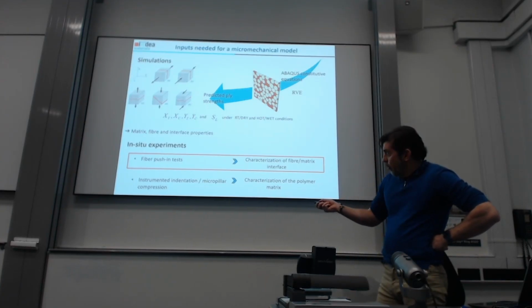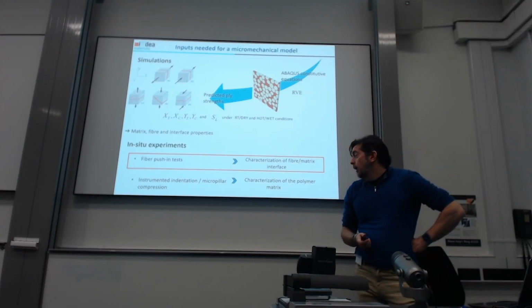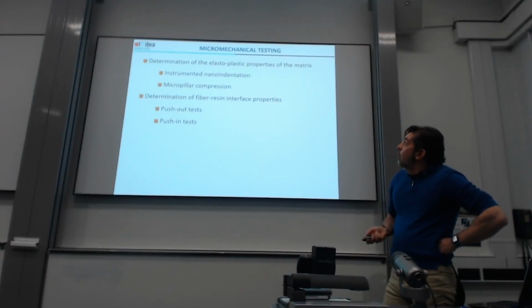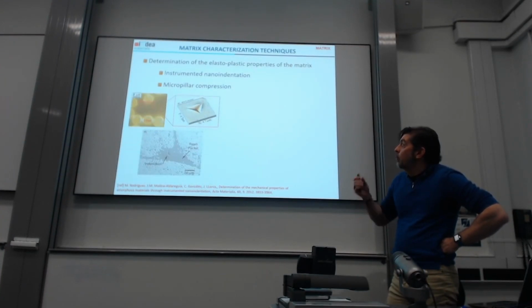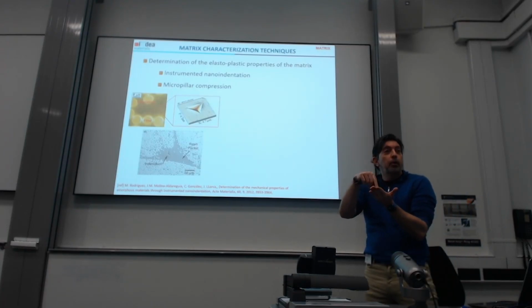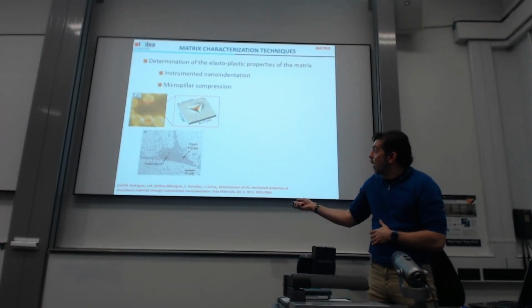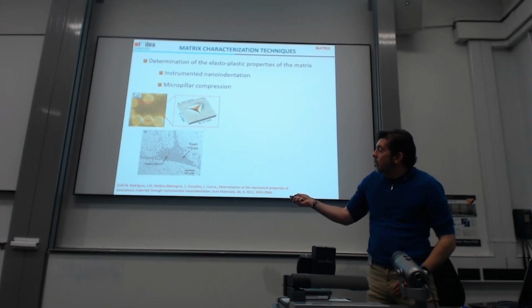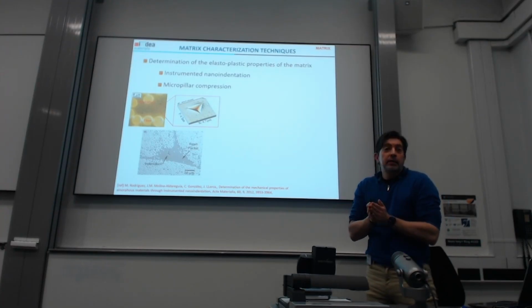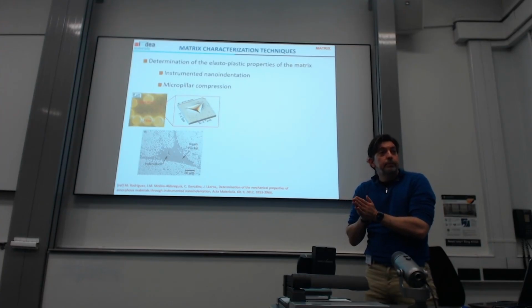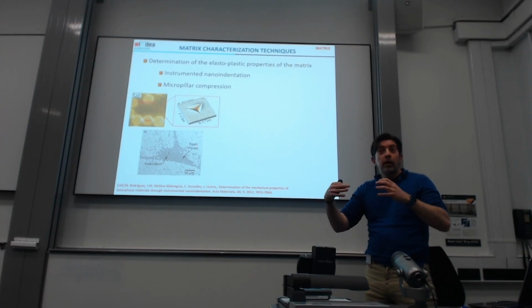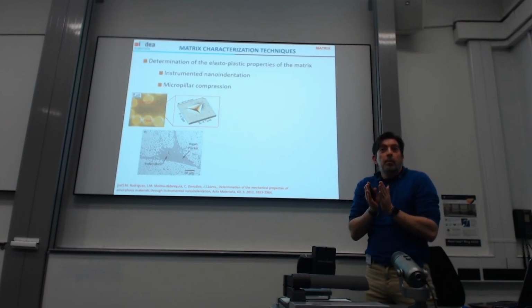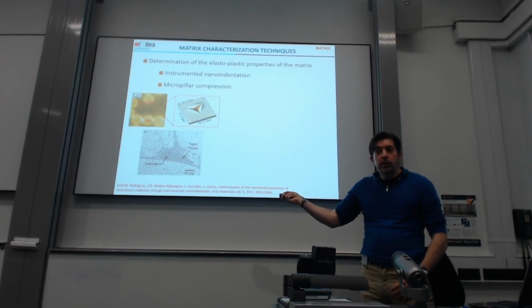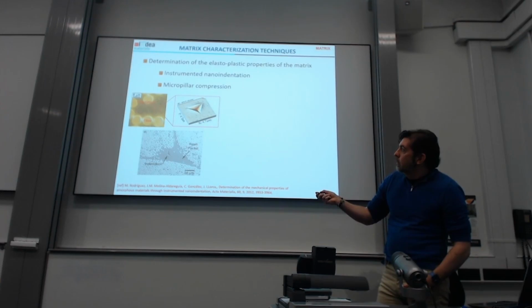For fiber push-in tests, we're going to use nano-indentation. I will just mention briefly the characterization of the polymeric matrix to get its elastoplastic properties. For the plastic properties, normally indents are placed in resin pockets where we have a lot of resin, and we obtain the apparent hardness and the modulus, and from that we can get the yield strength of the matrix in situ, taking into account all the residual stresses. We cannot test the matrix itself; we have to test the real matrix in the composite material by doing indentations.